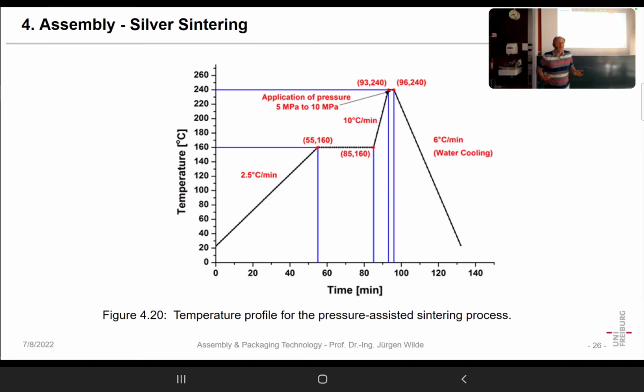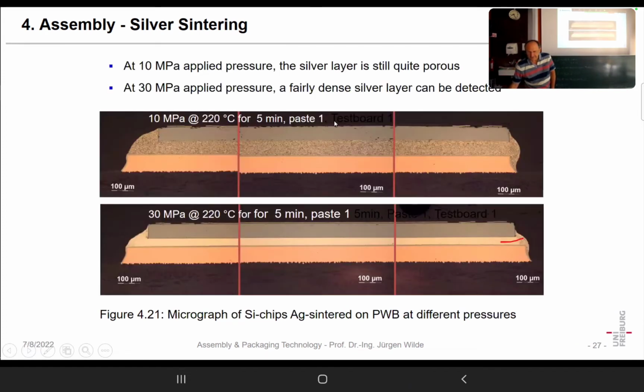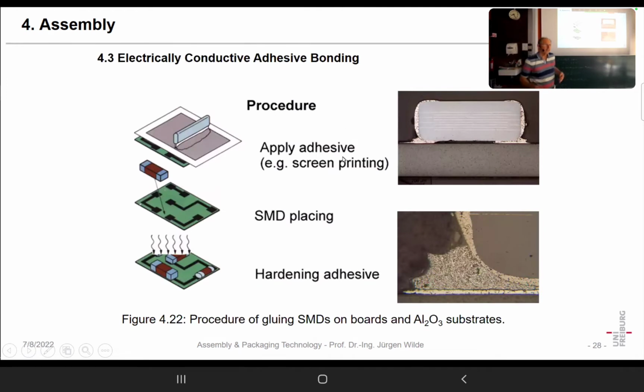And that's a typical profile, but we have seen in many cases when we have organics in a paste, we have a limited slope, holding time, and then going fast into the final process step where the interconnection is accomplished. Okay, that's about sintering.